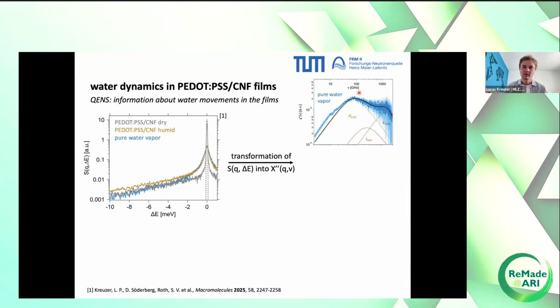And what do I mean with different dynamical contributions? So for pure water, we would have three. We have the diffusion, labeled with D, simply water molecule moving from A to B. Then we have another contribution at higher frequencies, meaning they are a little bit faster, these movements, denoted with L. This corresponds to a so-called local effective motion. These are movements on a local scale, faster than diffusion, but still slower than vibration, which come at very high frequencies, so water vibrations.